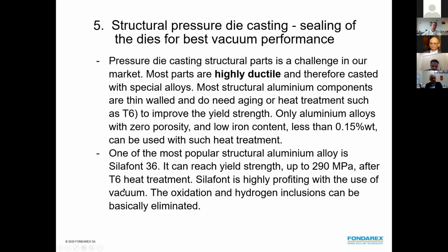Of course, today not everybody has the equipment for T6 heat treatments. There are some other alloys available, and even with Silafont and the standard treatment, we can already get more than 200 MPa, giving good castings which can be called structural castings. So the main thing is to reduce the oxygen and the hydrogen during the filling of the parts.